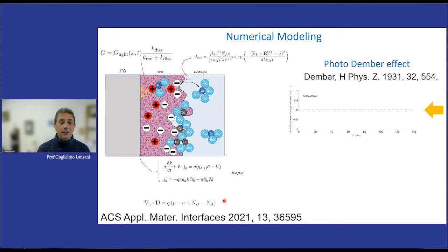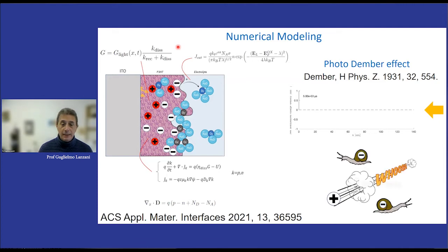So there is everything. There is a bimolecular recombination taken into account. There is a charge generation efficiency that generates about 10 to the minus 4 quantum yield of charge carriers. So we assume the light generates electrons and holes, say positive and negative polarons, with an efficiency of 10 to the minus 4. Now, the other ingredient that we put in this model is that the mobility of the electron is essentially zero. So the negative charges are essentially fixed, while the holes are extremely mobile.